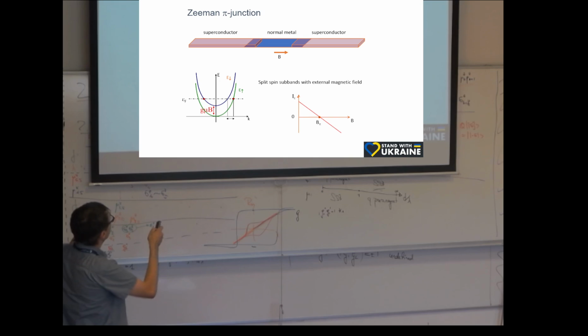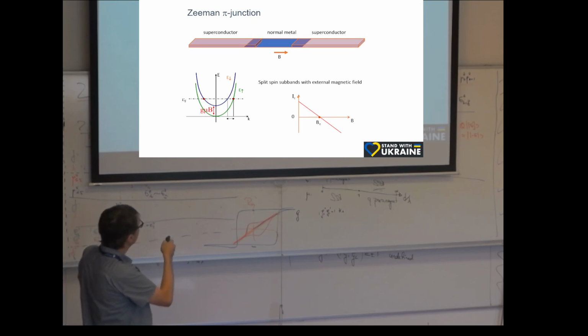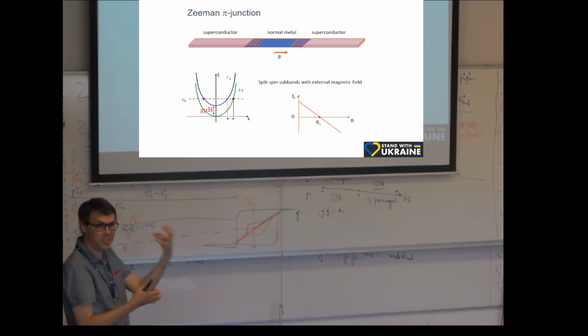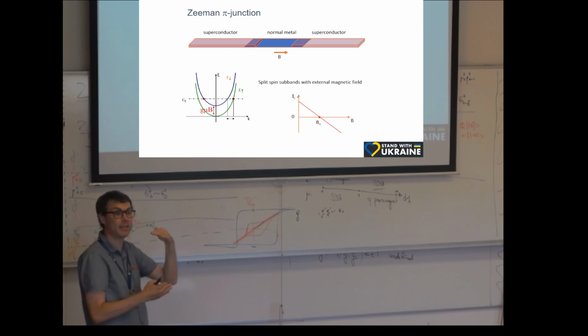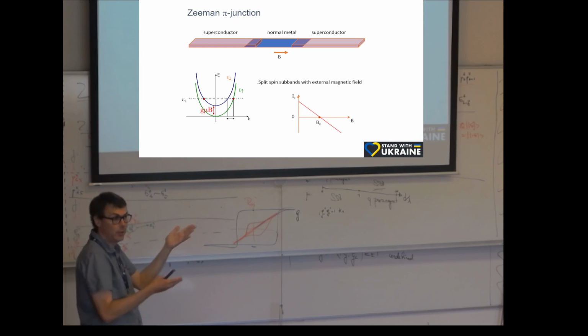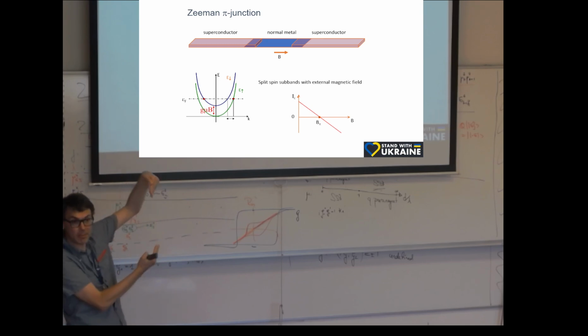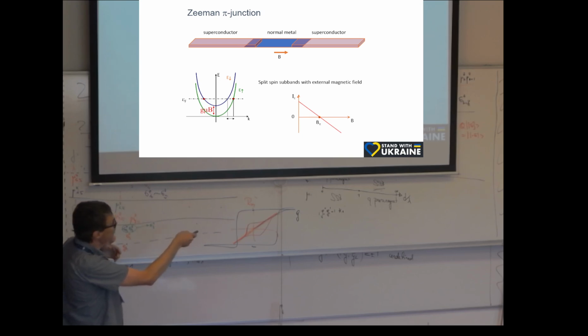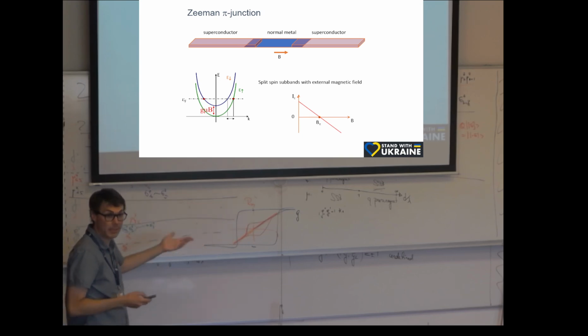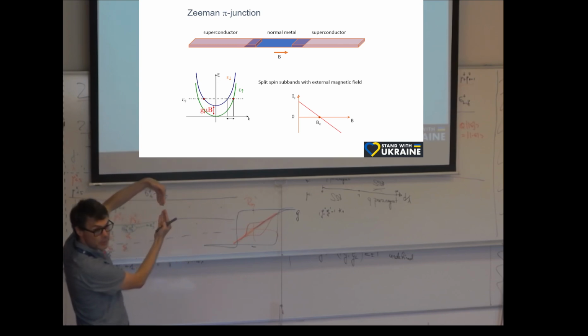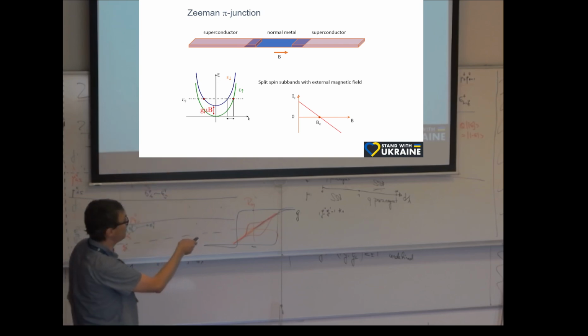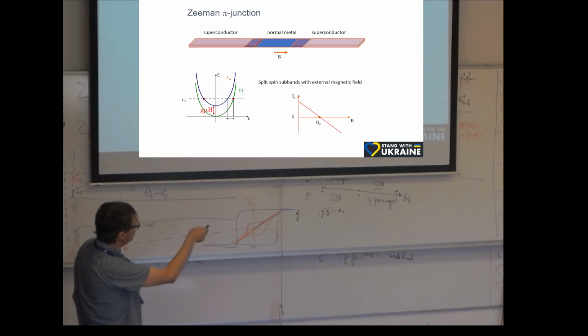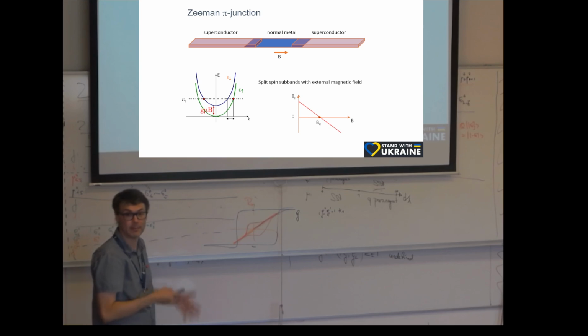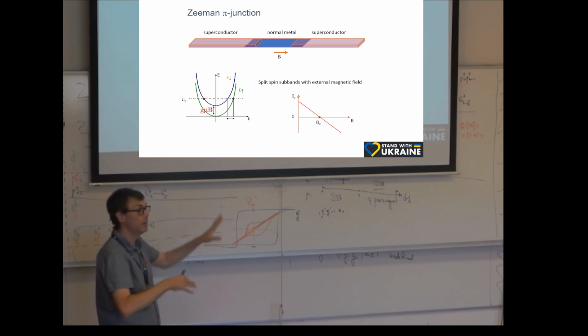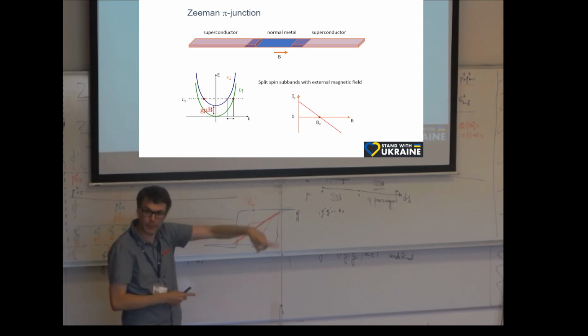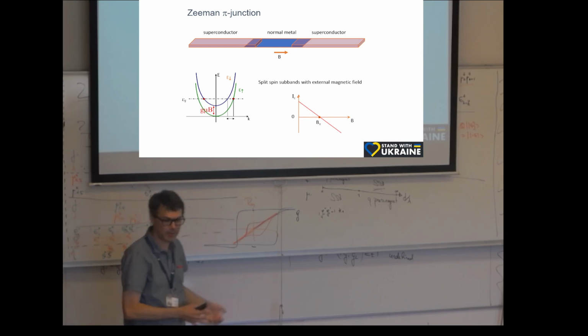I was thinking about this pi junction, the exact same idea, except the bands are split not by exchange coupling in a ferromagnet, but by external magnetic field. You can do the same thing, right? You apply magnetic field, and it will Zeeman split the bands, and we can have the same effect. And now the control knob is not temperature, it's magnetic field. The bands just gradually split, and at a certain field, which we call B pi, we go from 0 state into pi state. That's the idea. Zeeman pi junction, same physics, right? The oscillating wave function, real oscillation, driven by field.